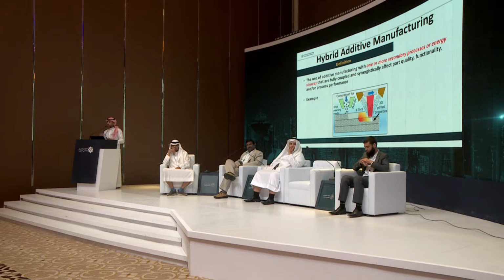The 3D printing terminology is common now, where you use a printer that prints parts layer upon layer. What we have done, and this got patented a couple of months ago, is you use 3D printing and you use a secondary processing at the same time, simultaneously. So you do printing and then you do processing in situ, inside the printing chamber. And then you print again and then you do the processing again.